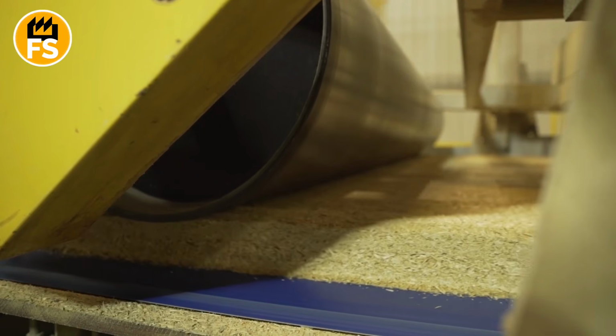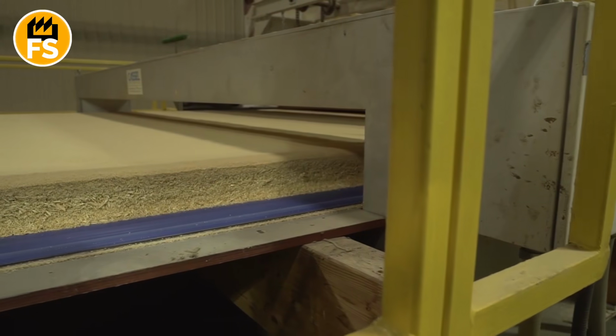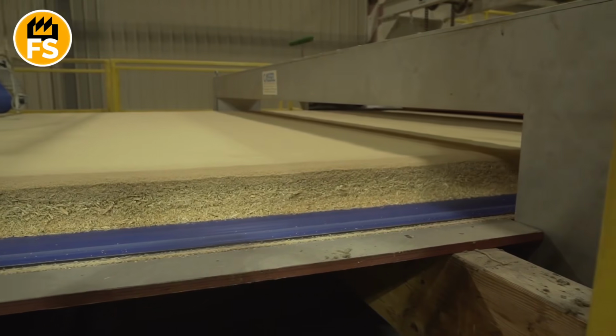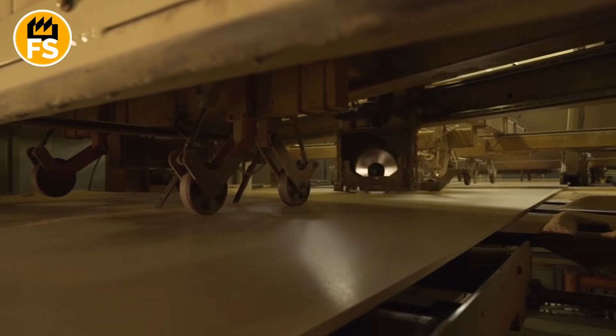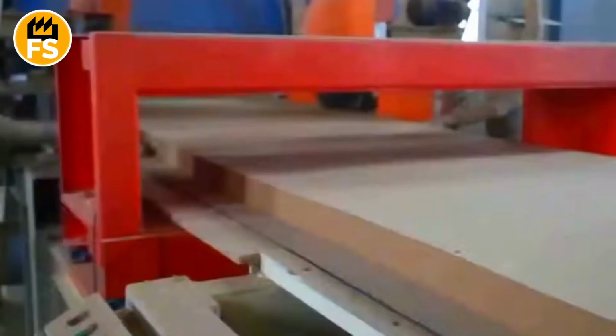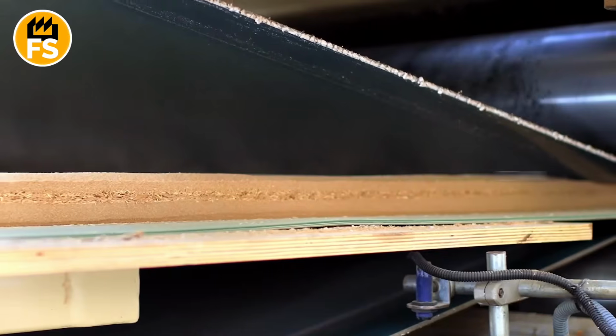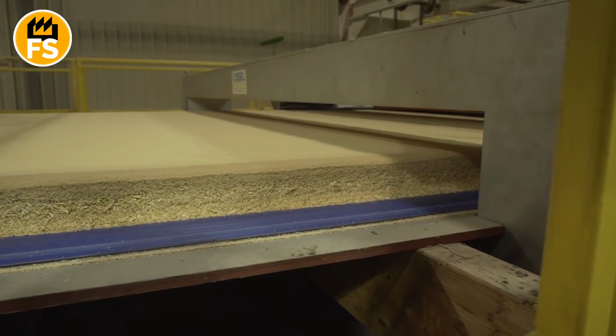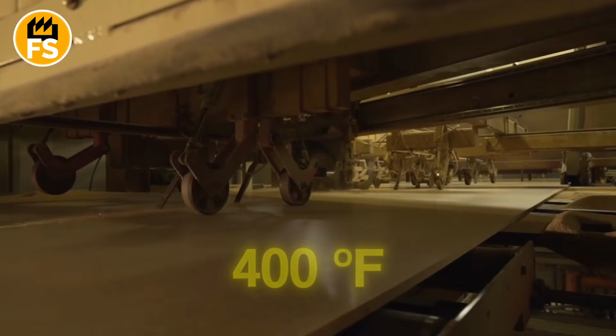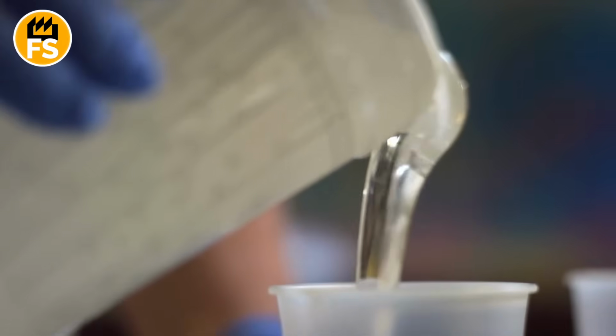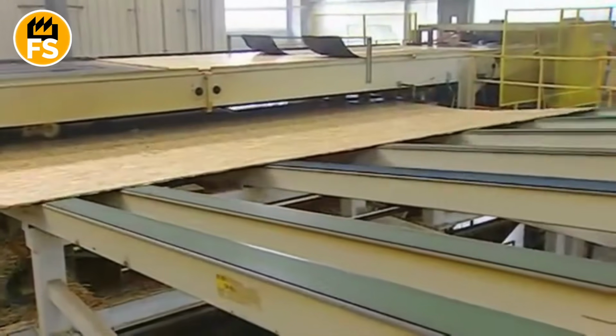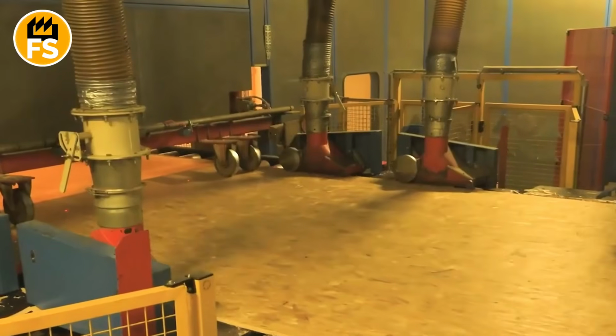This fluffy mat, which can be several feet thick, slowly moves to the final test, the hot press. This is a real industrial leviathan, a multi-story structure that creates colossal pressure and heat. The mat enters inside, and massive steel plates begin to compress it with a force of hundreds of pounds per square inch. At the same time, the press is heated to a temperature of 400 degrees Fahrenheit. This heat activates the resin, causing it to polymerize and permanently glue all the chips into a single monolithic shield. The wax also melts, even better impregnating the wood and filling microscopic voids. In a few minutes, the loose mass turns into a hard, incredibly dense, and hot panel.